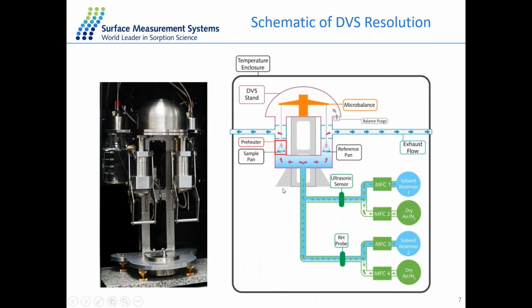So here's a schematic of one of our DVS instruments, the DVS Resolution system. This system can perform the sorption of both water and organic vapors. In the middle of this system, we have a microbalance, which is connected to both the sample pan and the reference pan. We will put the sample in the sample pan here, and the change of mass will be recorded by the microbalance. The carrier gas for the system will be nitrogen or dry air. And as you can see, there are 2 bottles at the back of the system. On the left-hand side is for water, and on the right-hand side is for the organic vapors.